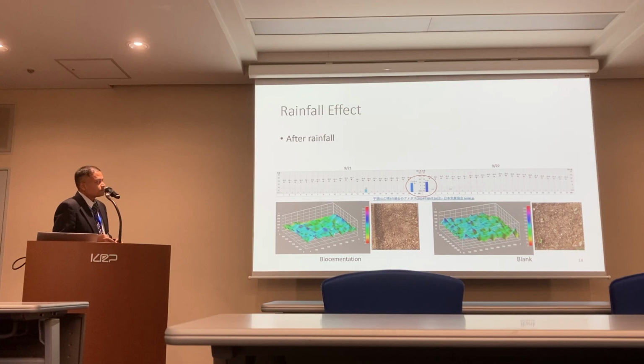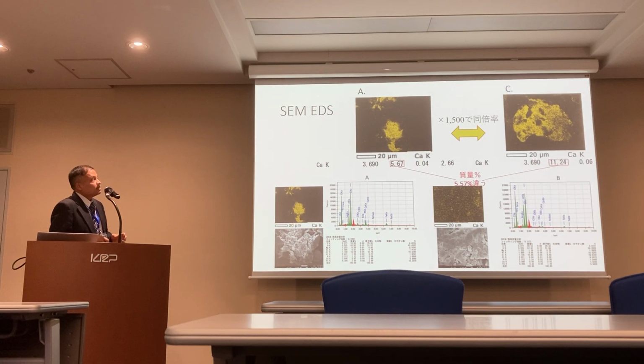Then we checked the scanning electron microscope images, and we found that both A and C are biocemented, but one is with grass and one without grass. Without grass, the calcium carbonate is much more than with grass. Maybe we applied the nutrient solution in liquid from the surface, so some of that is hindered by the grass or leaves of the trees.